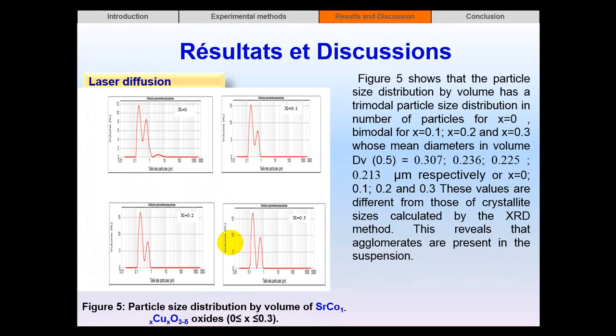For the laser diffusion, figure 5 shows the particle size distribution for the different samples. It's observed that there is a trimodal distribution for the sample x equals 0, and a bimodal distribution for x equals 0.1, 0.2 and 0.3, whose mean diameters in volume equal 0.307, 0.236, 0.225 and 0.213 microns respectively for x equals 0, 0.1, 0.2 and 0.3. These values are different from those of the crystallite sizes calculated by the XRD method. This reveals that agglomerates are present in the suspension.